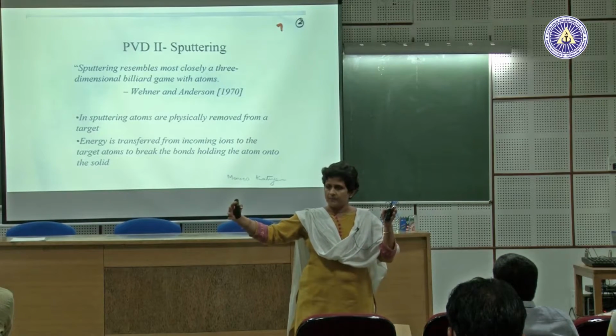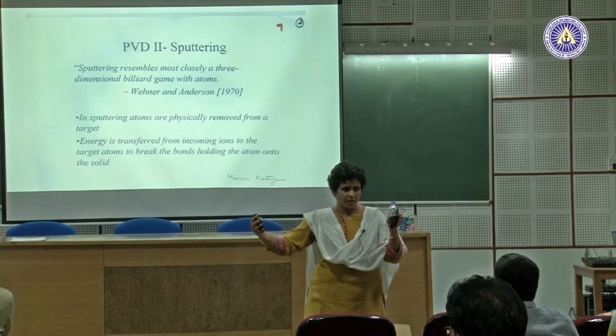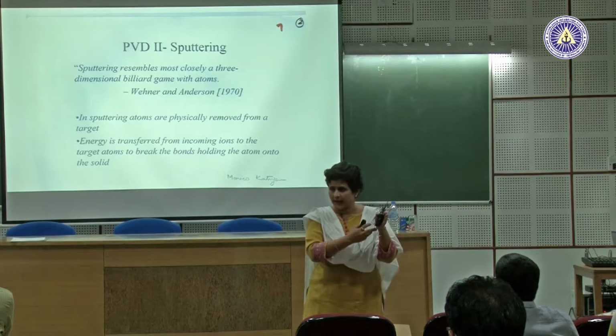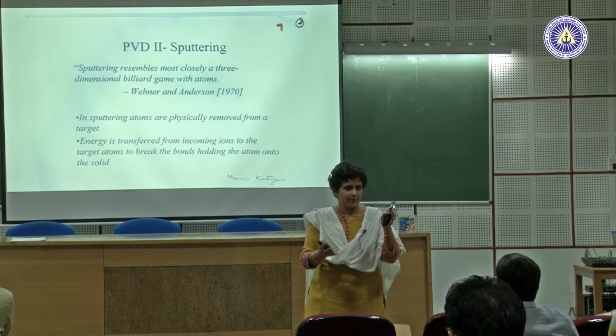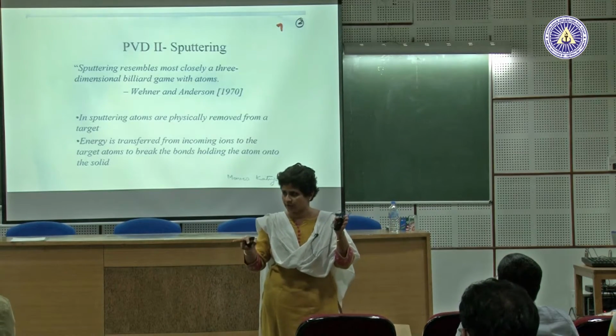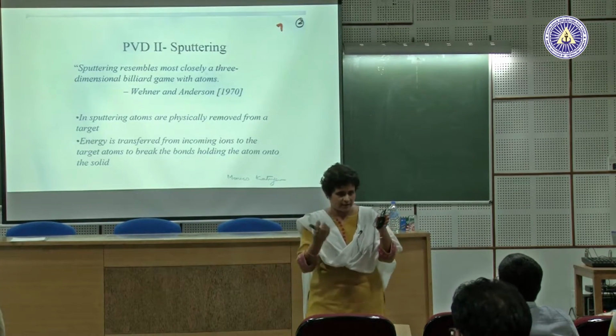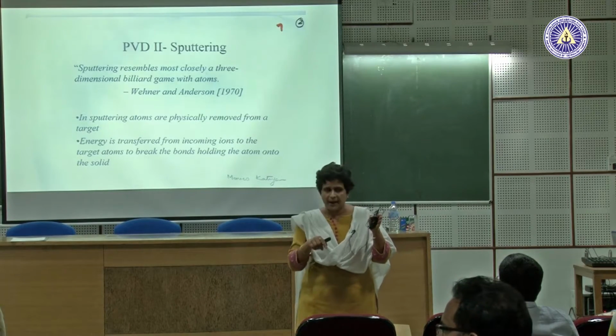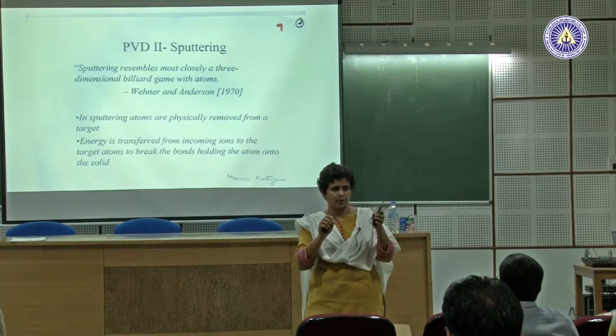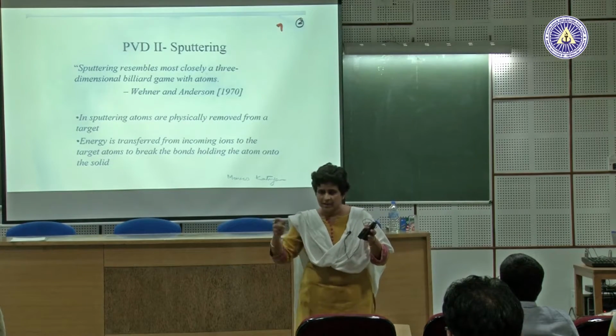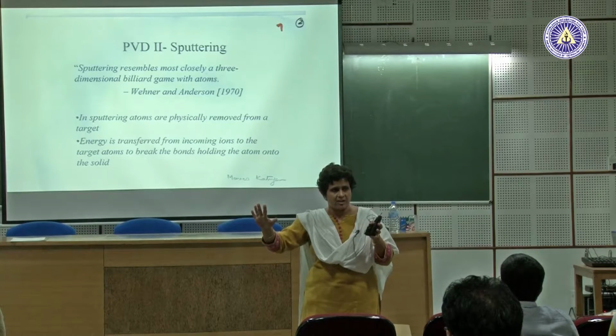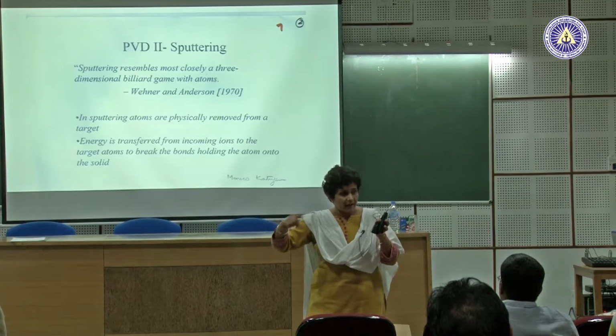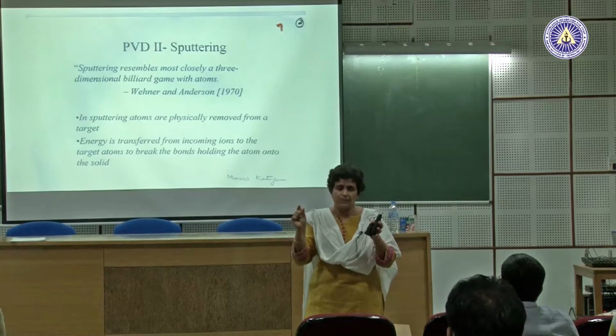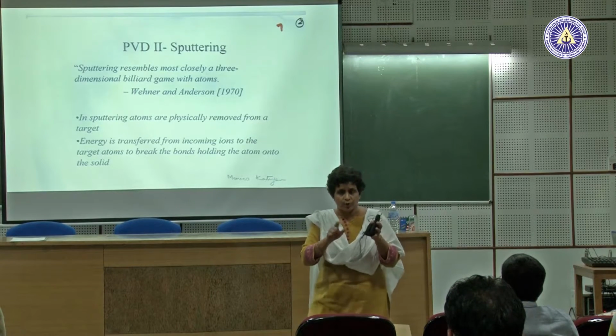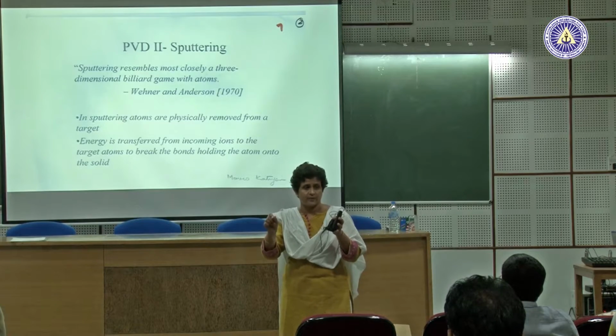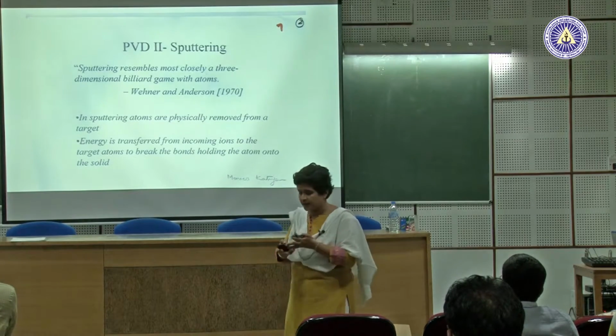Okay. Now, the first thing which is very clear, different from evaporation: since I am sputtering off an atom, the energy of the sputtered atoms is much higher than in the evaporation process, where it is only the thermal energy that is given from the evaporation, right. Now, it has impact on the film. These are generally used for hard coatings, because when you are bringing the atoms at a higher energy, they would interact with the substrate with a higher energy and get implanted in the substrate and get a better bonding and better intermix layer. Okay. So, sputtering generally is used where you need hard coating, you need good properties at the interface, because the atoms are coming at the higher energy.